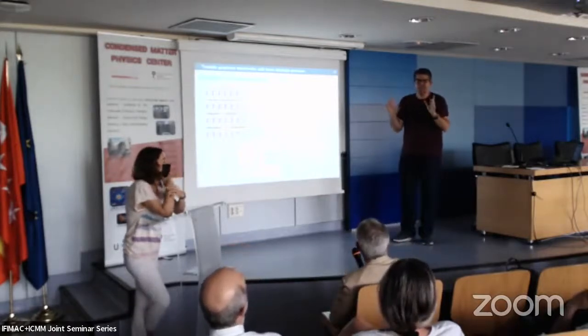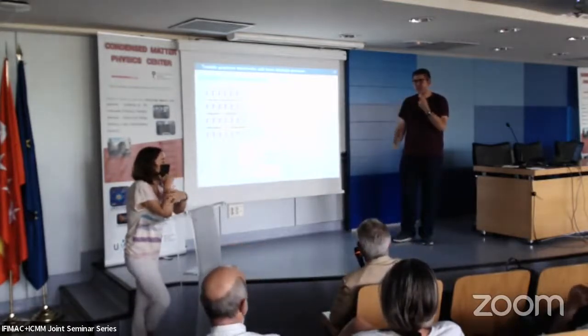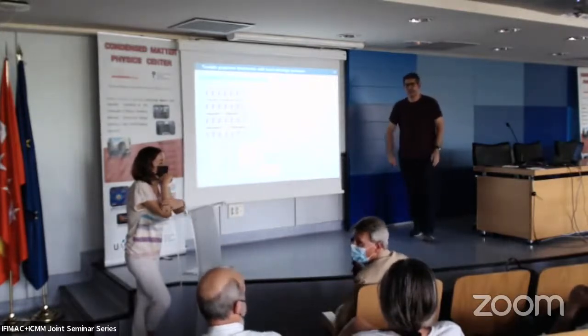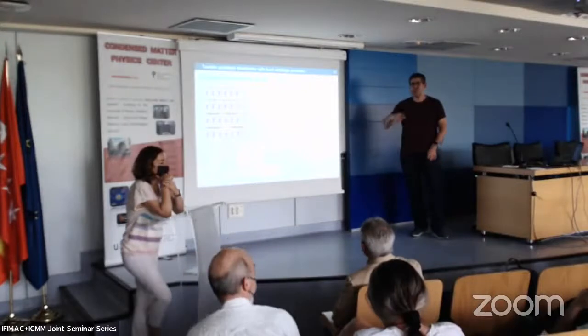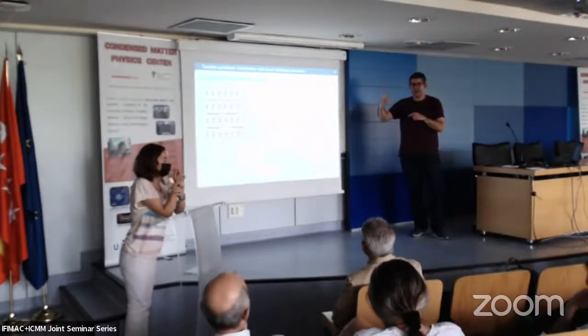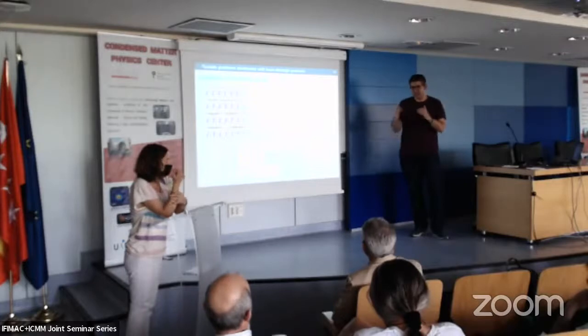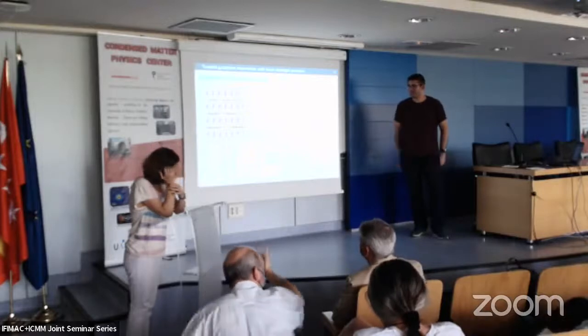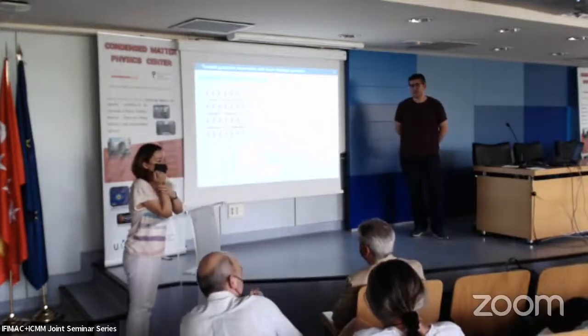I remember you simulated it. I don't know if it was 100 atoms or 100 by 100. Yeah, it was huge. And in that amount, just one or two atoms only, yes. Even less. It was 1%. I would say 1-2% is like an upper bound. We did not go further with the simulation because it was completely out of resources. But yeah, less than 1% were enough to explain this charge transfer and the fact that the graphene remained. That's why you see basically the same peaks as for pristine graphene. These bonds are less than 1%. Okay. Thank you.